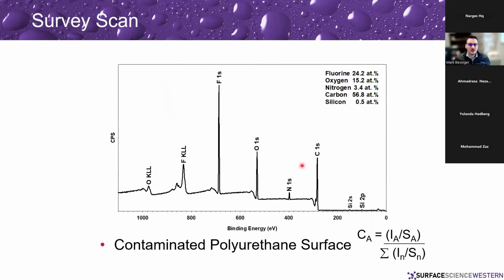General analysis usually starts with what we call a survey scan. This is where you scan the binding energies from 0 on up to, say, 1100 or 1200 eV, and you get peaks that look like this that can then be assigned to the various elements that are present. So if you have something at 285, you've got carbon, you've got an oxygen peak here.